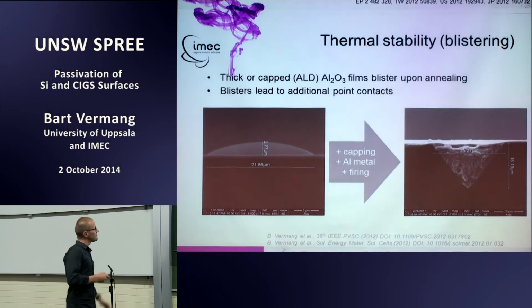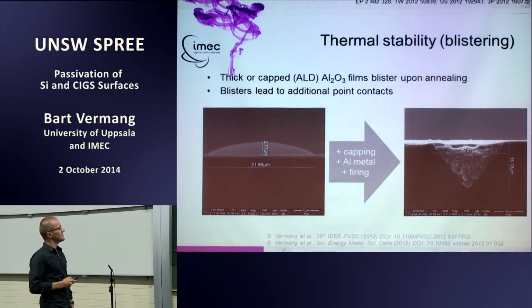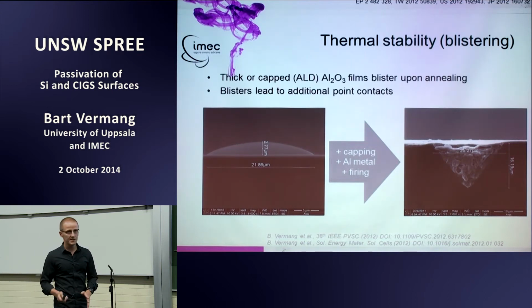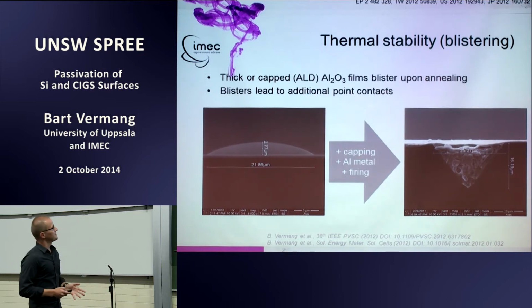So the first topic I would like to briefly discuss is thermal stability. One of the things that happens with ALD aluminum oxide, and as well with PECVD or plasma enhanced ALD, but at different temperatures and in different circumstances, is if you have an ALD aluminum oxide layer and it's quite thick, more than 10 nanometer, or it has been capped with silicon nitride or silicon oxide, if you then bring it to a higher temperature, you might have something which is called blistering. So there might be bubbles in your aluminum oxide layers, which is not really beneficial, because in the end we are using ALD layers or aluminum oxide layers as a passivation layer, so they're always capped with metal layers.